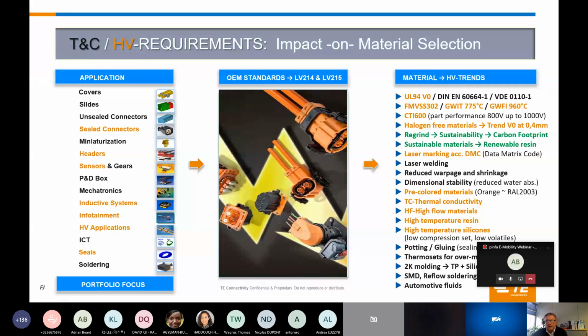If you go for improved materials like PPA ones, independent how they are modified, we could achieve 600 volts up to 800, 850 volts. Maybe the measurements are not stable enough due to different reasons already mentioned in the former presentation, but there are some indications on the market that PPA materials are better candidates if we take the actual test method and we go up to 800 volts, max 1000 volts to be visualized also in the future.